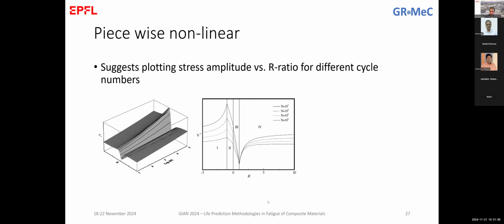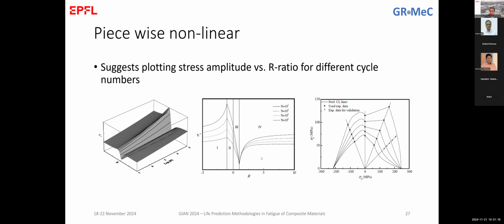The CLD looks like that, where again you have four different regions, one for tension, one for compression, and the other two for mixed loading. And there is also a simple interpretation. It's like the piecewise linear, but instead of having linear interpolation between the known values, you have a nonlinear interpolation by parameters that are fitted to the available experimental data. So with this, I summarize the description of CLDs.